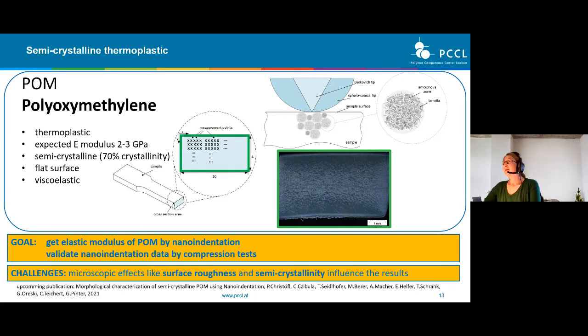And what you can also see here on the right side of your screen is that we have a high crystallinity, and the crystallinity is not homogeneous all over the sample. So we have at the edge of the sample a lower crystallinity and a higher crystallinity in the middle of the sample. And the goal of these investigations with nanoindentation was to get the elastic modulus of POM by nanoindentation, and again to validate the nanoindentation data by compression test. The challenges here were microscopic effects like surface roughness of the sample and the semi-crystallinity, which influence the results.